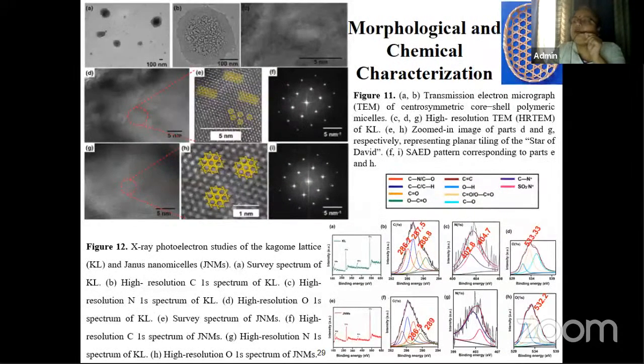So as I told you, the morphological and chemical characterization, you see, Kagome is a Japanese basket. So we are seeing this type of arrangement with the help of TEM results, HRTEM results, and the SAED pattern as well as the FFT. So we have also done the core-shell structure analysis, that is XPS, because FTIR only shows the valence-shell phenomena. We have to go to the depth to understand the mechanism of formation of these exotic nanostructures.